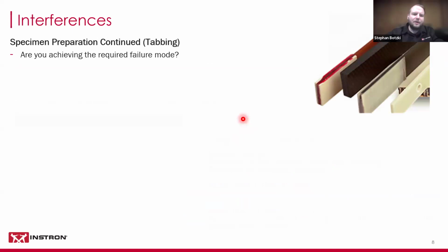Now, one question when we talk about tabbing is, are you actually achieving the required failure mode or modes within the testing standard? So if you are having a successful test where the specimen fails in the gauge section and you have the right type of failure mode, you probably wouldn't even want to consider any tabbing because you're doing what the testing standard is asking and you're achieving the right results. Now, if you have any kind of grip failures or you're outside of the gauge section where the majority of your failures happen, then that is a time to really think about your process and consider using tabs.